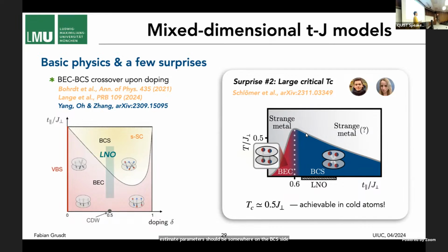And this means, because you're close to the BEC to BCS crossover, that you can have extremely high critical Tcs for superconductivity. If you estimate this in this toy model, we find 0.5 times J perp for the Tc of the condensation. And if you translate this into numbers, this can be around 1000 Kelvin. Now, our model, of course, is too simple, which is why it's not the 1000 Kelvin that they actually measure. We're not worried about this.